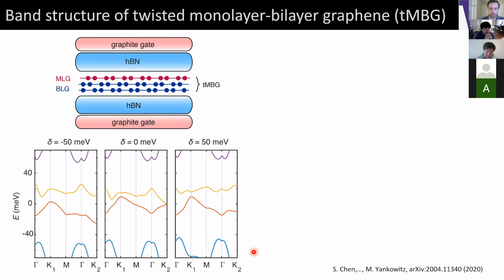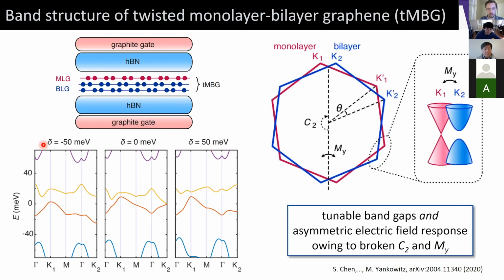But now there's a new ingredient. I have to show you both calculations for positive and negative electric field. The system has reduced symmetry still from the twisted double bilayer graphene, which was symmetric with electric field. Now we're breaking an additional symmetry, which is this mirror symmetry in plane. And this MY mirror symmetry basically exchanges the top and bottom components of this heterostructure, or more formally, it exchanges the valleys within the Moiré-Brillouin zone.